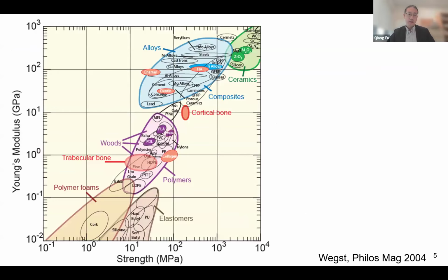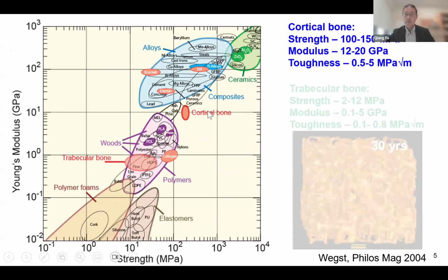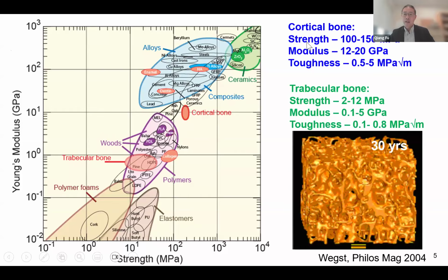This strength versus modulus plot shows how natural materials, polymers, ceramics, and also bone compare. If you look at cortical bone, the strength is definitely much higher than trabecular bone. I put the numbers here. Cortical bone has a strength of about 100 to 150 megapascal, and also much higher toughness. In comparison, trabecular bone has a much lower strength of 2 to 12 MPa.